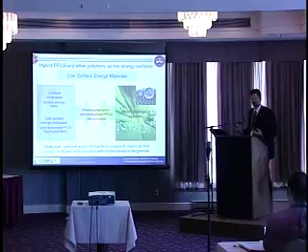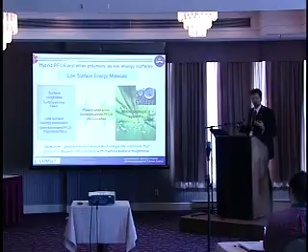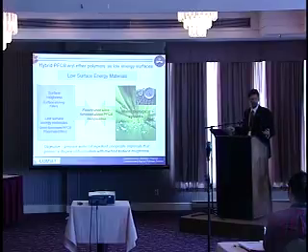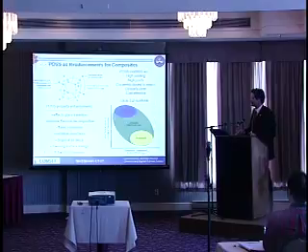They bloom to the surface and they give you nano roughening, and we know enough about the lotus leaf and self-cleaning and ultra hydrophobicity, ultra oleophobicity, to know that it's not about micro roughening, it's about nano roughening. You have to have the right type of surface roughening, and you throw in inherently low surface energy bonds like fluorocarbons, so you get a synergistic effect. And we've been working with this.